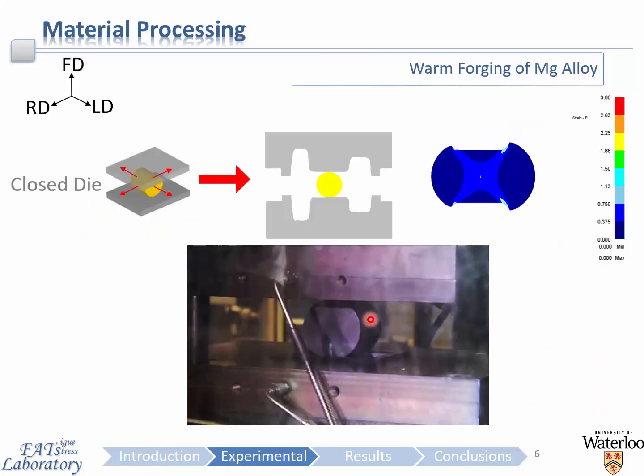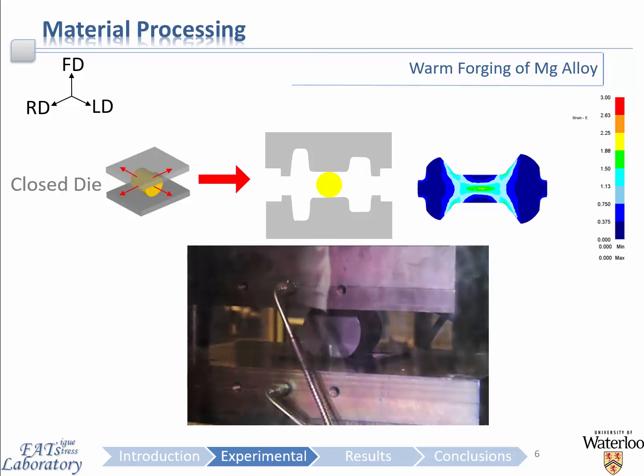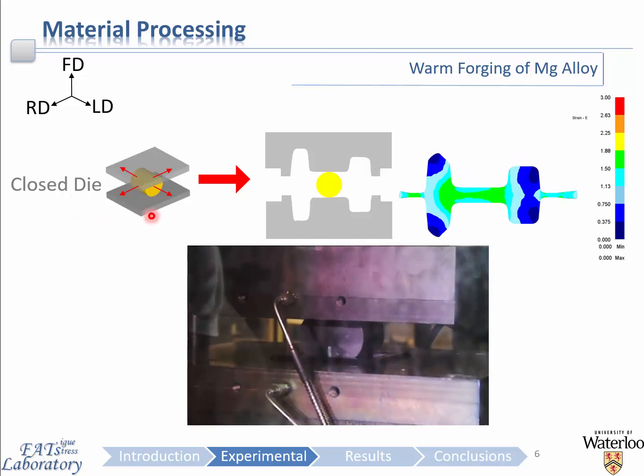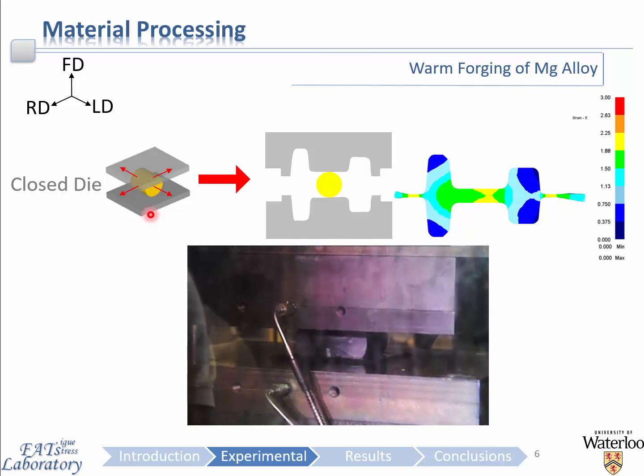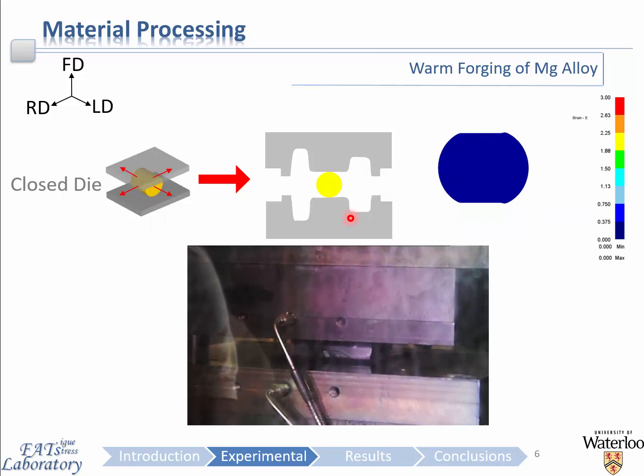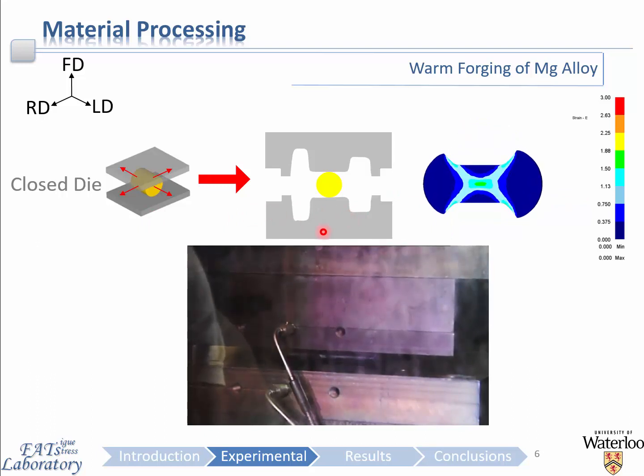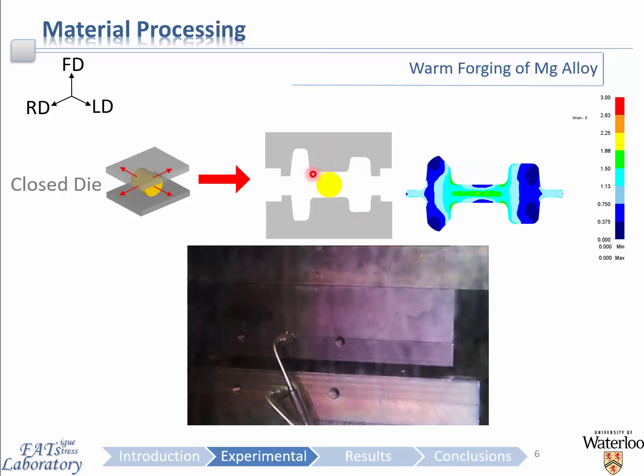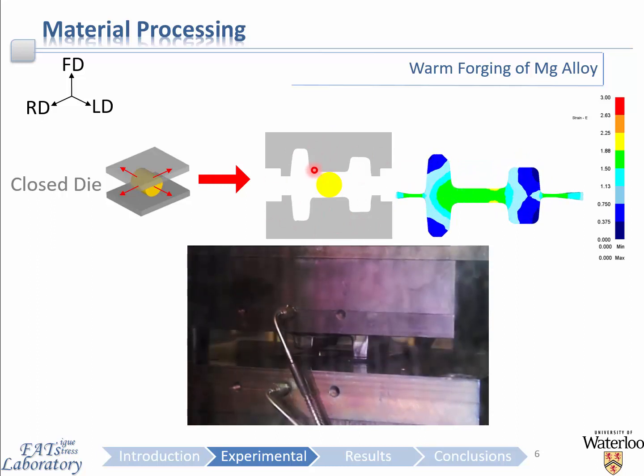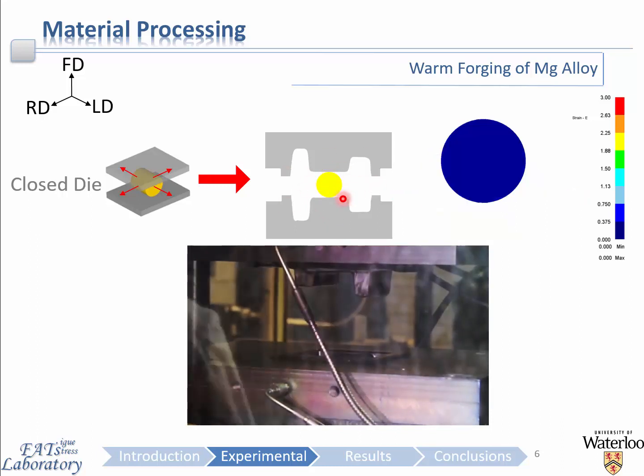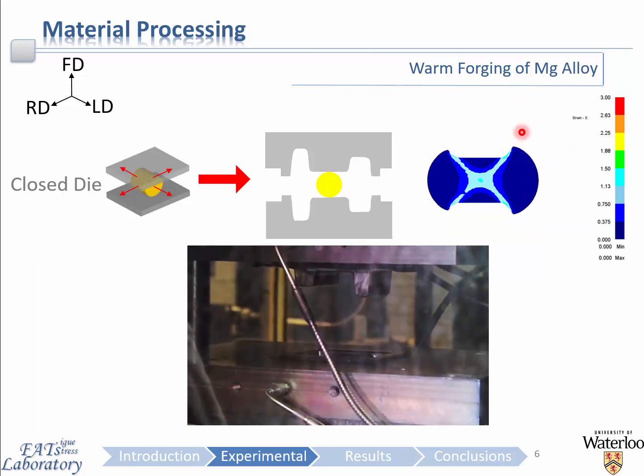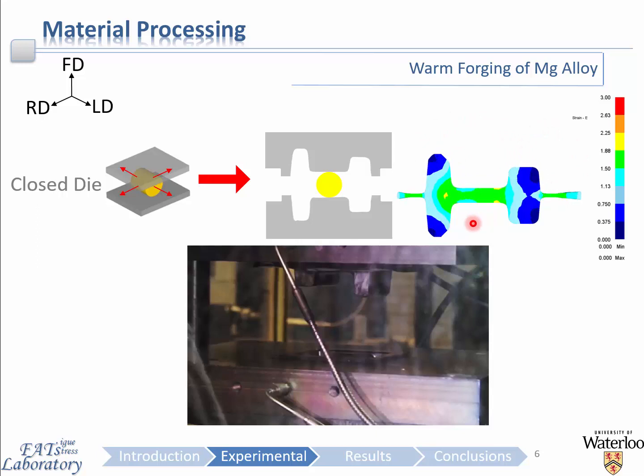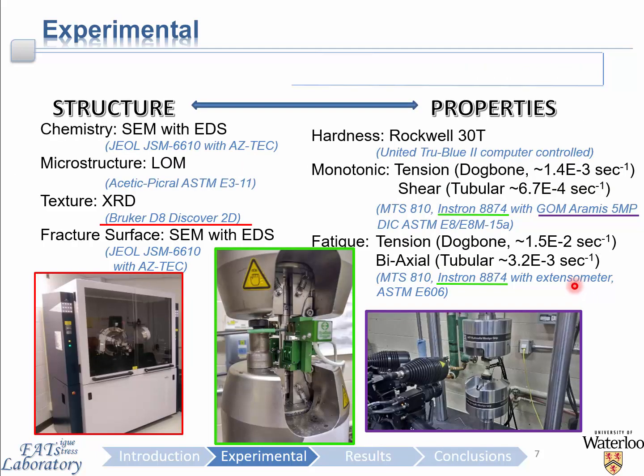The material utilized to produce test specimens was produced using a closed die forging technique. The initial cylindrical billet shown here was heated to various temperatures and then forged at 20 millimeters per second in heated dies which restrict the material flow in both in-plane directions. These dies have this internal I-beam cavity, which is typical for structural components which try and maximize bending stiffness to have this high inertia cross-section. The contour plot on the top right shows the evolution of strain throughout the cross-section of the forging, predicted through a finite element model. It can be observed that the billet undergoes the forging process from a circular cross-section to this I-beam profile.